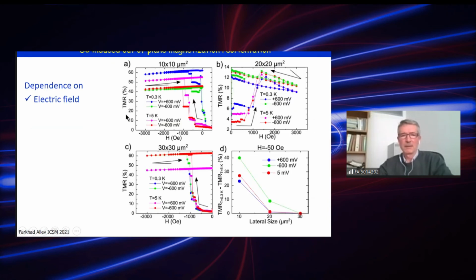In the very last slide, the effect is also affected by the presence of electric field, and bigger effects are observed in the smaller size samples where the out-of-plane anisotropy is larger.